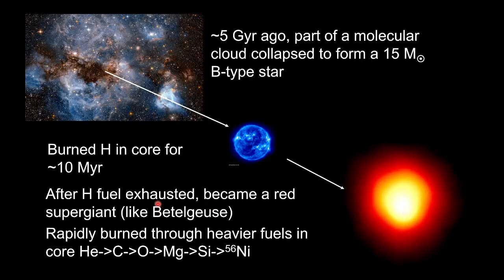And then for a while, it rapidly burned through heavier fuels. In this case, the helium burned to carbon, but then that core collapsed and started burning oxygen and carbon to magnesium, to neon and other heavy elements, to silicon, until eventually it became nickel-56 in the core. Nickel-56 is the most stable nucleus, which means that beyond that, you cannot make any energy by fusion, because you don't have any more exothermic fusion reactions.